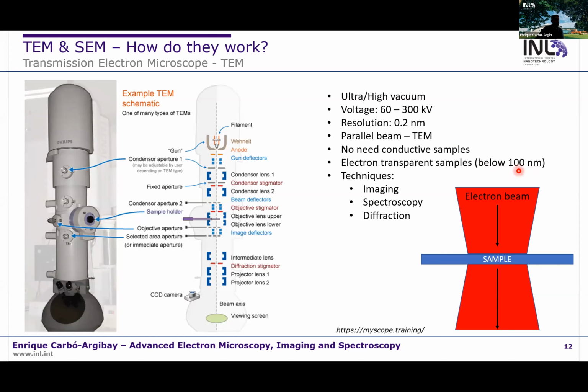So in TEM, the sample prep is a bit more difficult than in SEM. In SEM, we just need conductive samples, and this is something that we can get easily with a layer of carbon or some metal. However, in TEM, we need thin samples, and in case we have a bulk material, we have to do a previous sample prep to cut a piece of our sample and reduce the thickness to 100 nanometers or below. The advantage of the TEM is that the resolution is much better than in SEM, at least 10 times better. The voltage we use is a bit higher. In the SEM, we talk about 1 to 30 kV. Here we talk about voltages from 60 to 300 kV. And also we have 3 different groups of techniques: imaging, spectroscopy, and diffraction.